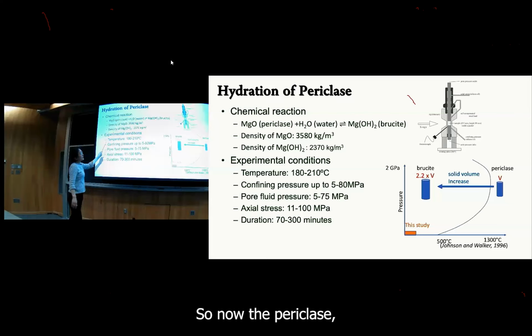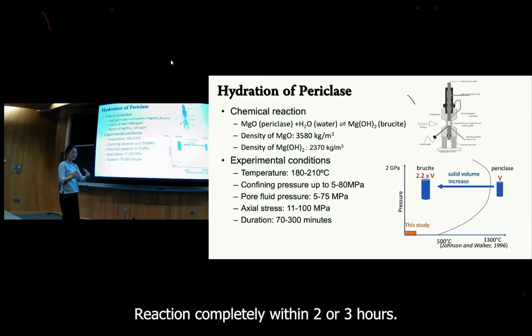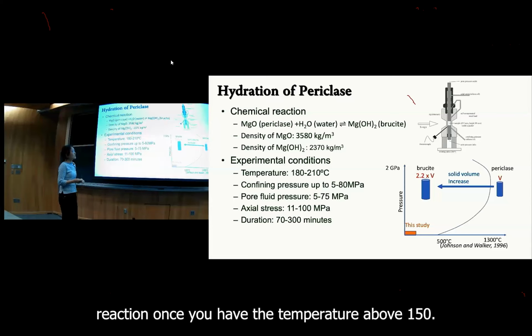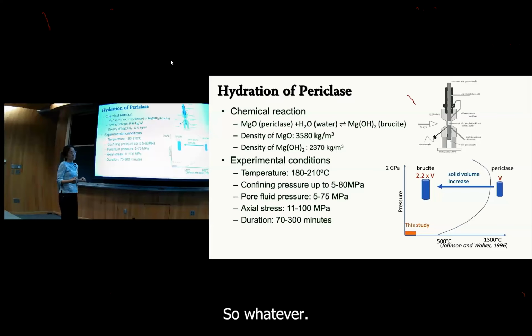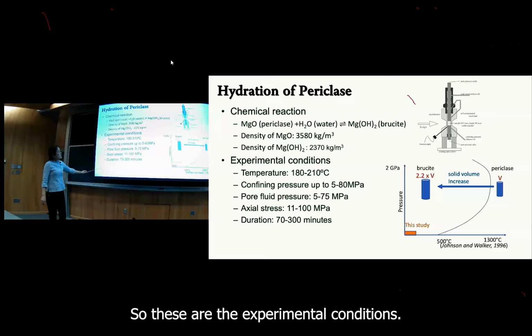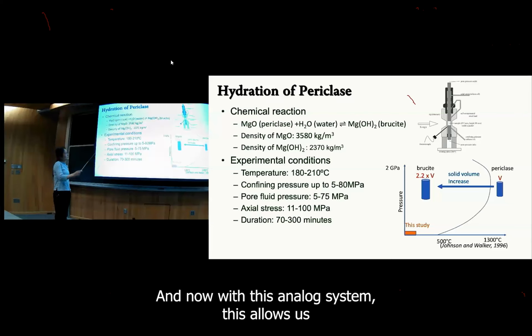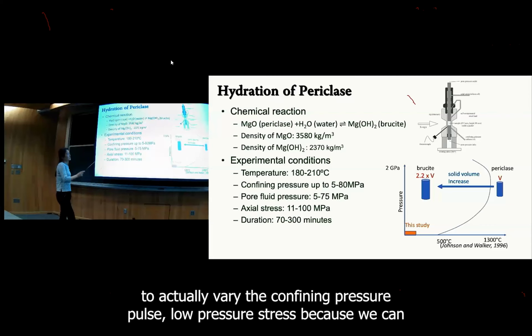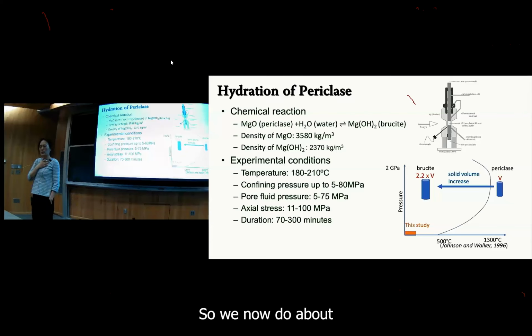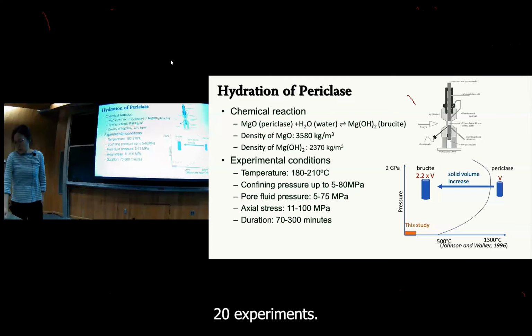So now for the periclase, the temperature range is 180 to 210 degrees C, because this will allow us to see the reaction complete within 2 or 3 hours. You see significant reaction once the temperature is above 150. If it's just room temperature, it takes forever. So these are the experimental conditions, and this analog system allows us to vary the confining pressure, pore fluid pressure, and stress, because we can do more. Like I said, we now do about 20 experiments.